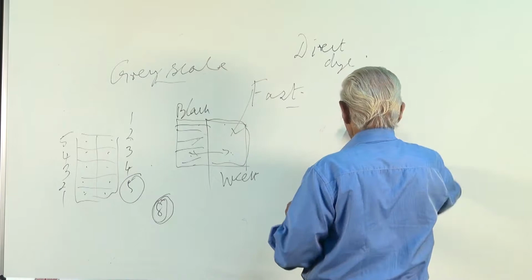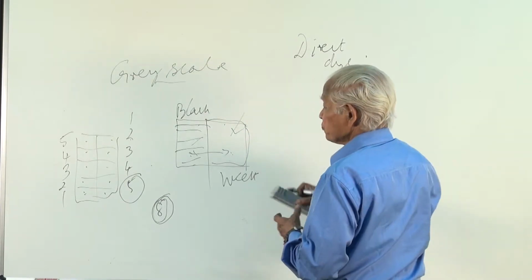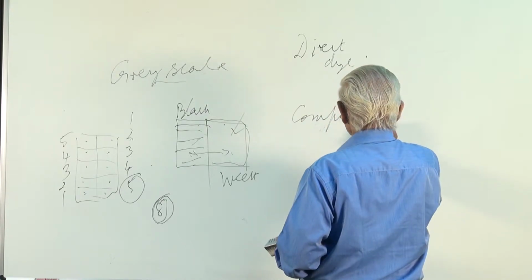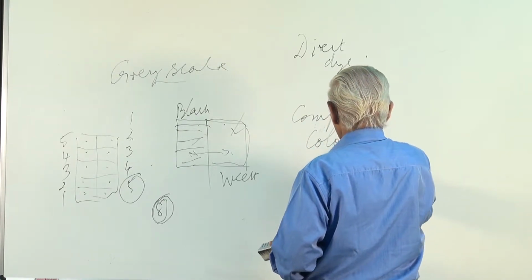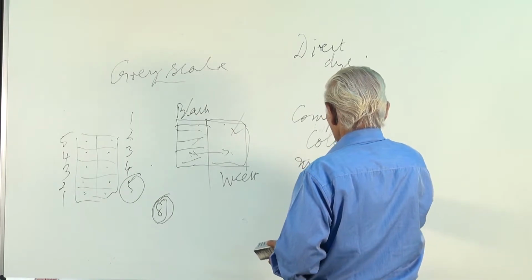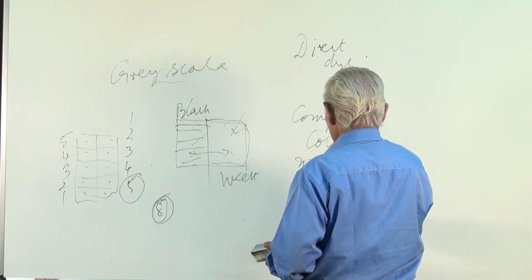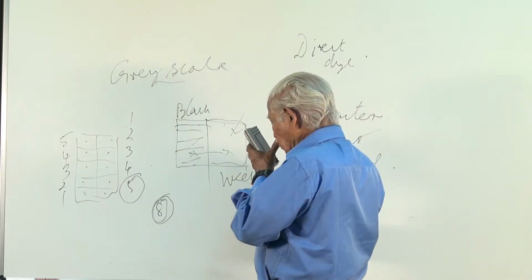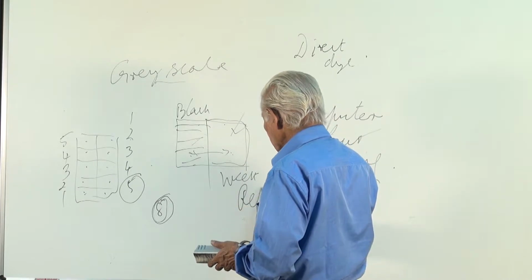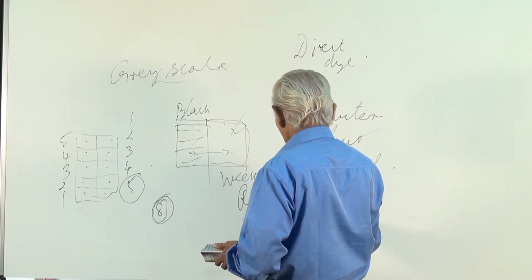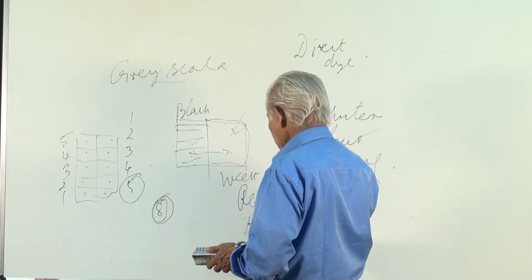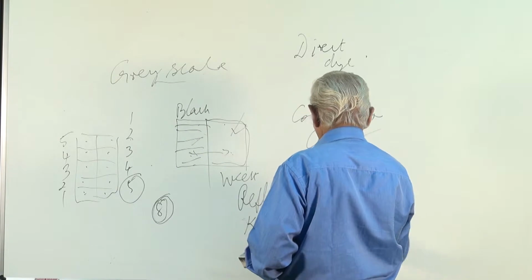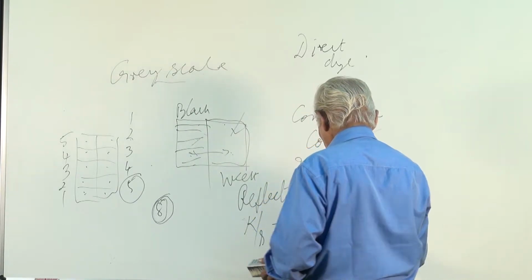And the scientific way of assessing the fastness property is to use a computer color matching system. Here we find out the reflectance value from which the K/S value is calculated, (1 minus R) the whole square divided by 2R, where R is the reflectance.